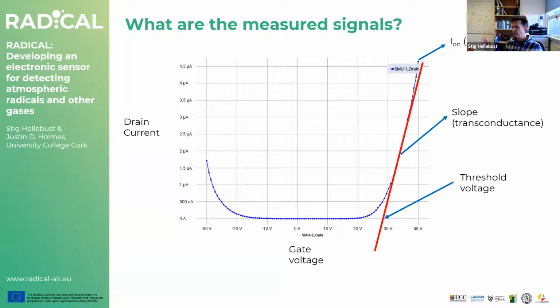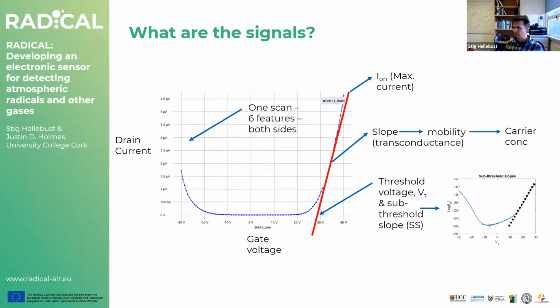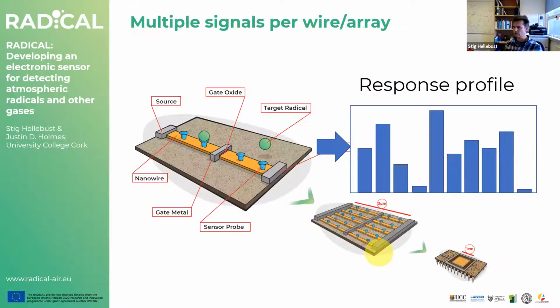So far we have three things, and this depends on the shape of that curve. It's essentially the shape of that measurement that lets us extract the features of interest. But from these three, there are also three more. Justin mentioned the carrier concentration, and we have something called mobility, and then there is something called the sub-threshold slope. Down in this low region, if we look at it on a logarithmic scale for the drain current, there is another slope, which turns out to be quite important. So now we have 6 features times 2, because these devices are ambipolar. So we have 12 features to start with, and then we've got to figure out which ones of these are actually useful for the sensing and the calibration part.